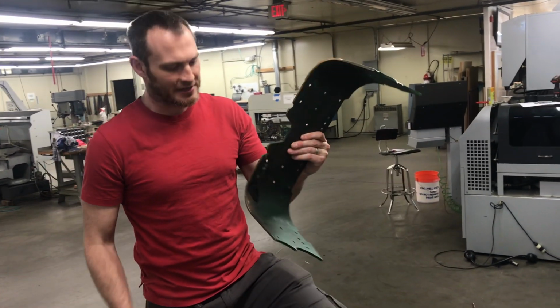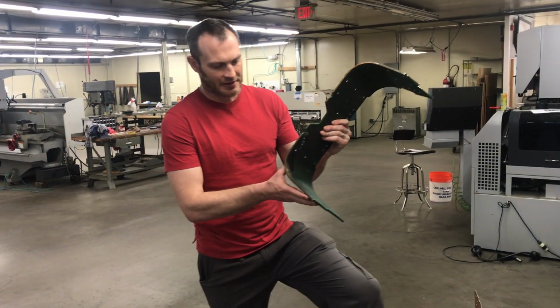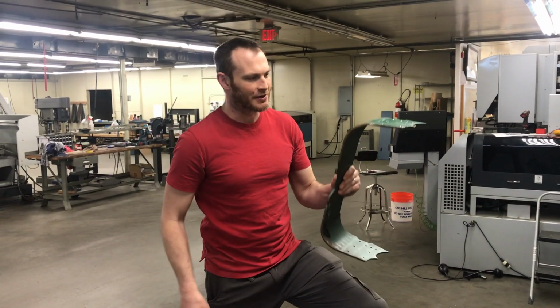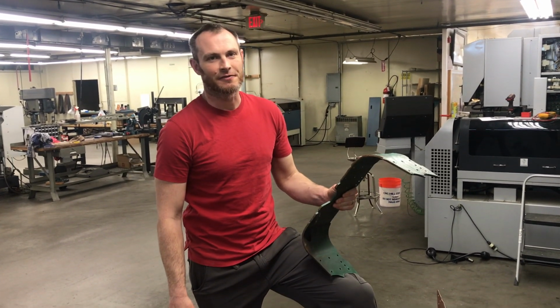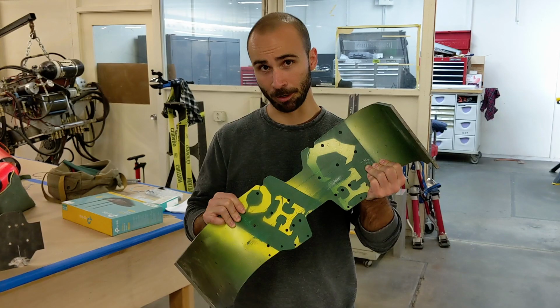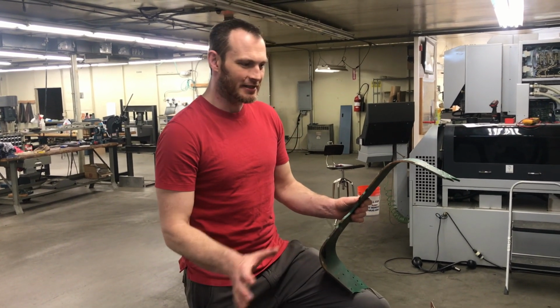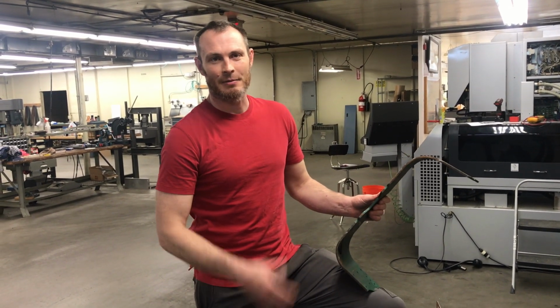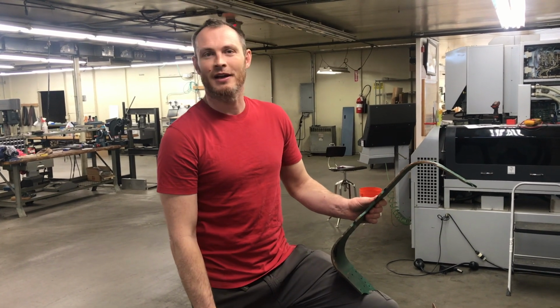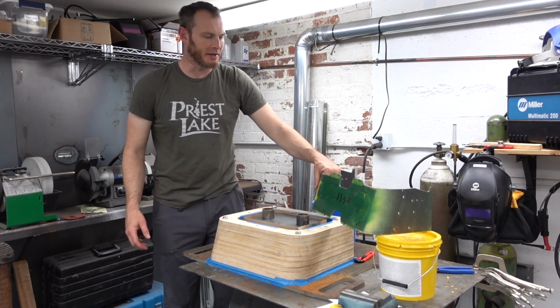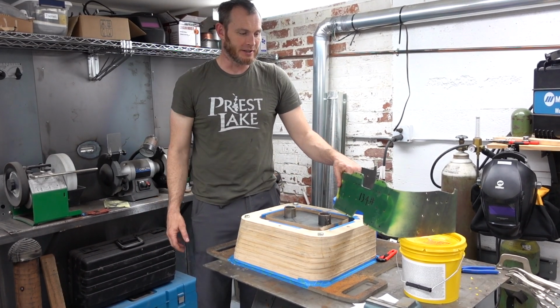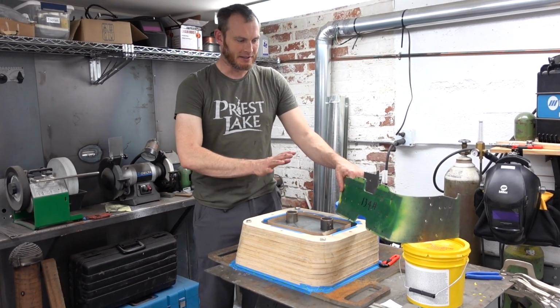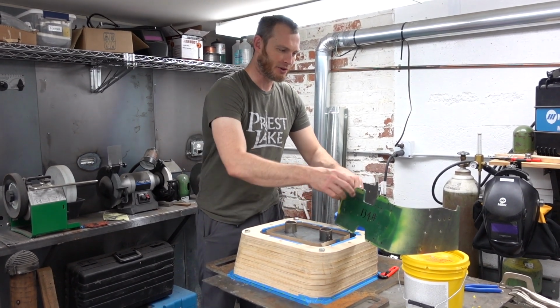This piece is the correct size. The bends bring these 2 faces to the correct dimension, but that was definitely not the case with the first piece. The piece that you see tested in the crate is our first article that we had quite high confidence would be wrong. We bent it to the nominal bend lines, and then we measured how wrong it was, and then we just corrected our bend positions by that error. So this is the first piece of armor we bent. It's a perfectly good piece of AR-500 that we can use to test the effectiveness of this armor in the crate.